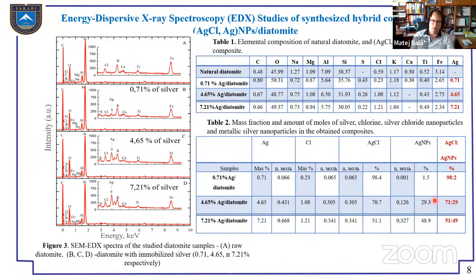Okay. I guess this is just my recommendation, and if I had the same results, I would maybe also use XRD analysis to determine the ratio between silver and silver chloride. It can be done by various methods, like Rietveld refinement, for example. In this way, it is more often used than determining the ratio using SEM EDS, but of course that is also a way to do it. So that's just my comment.